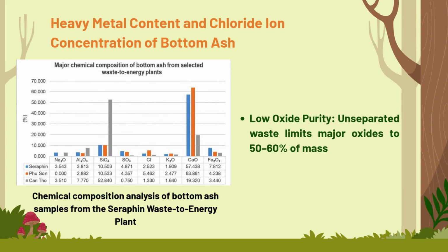However, together they account for only about 50 to 60% of total composition, which is lower than value typically reported in developed countries. This is mainly because municipal solid waste in Vietnam is not well separated at source. The EDS analysis confirms the presence of major elements such as calcium, oxygen, carbon, silicon, and so on.